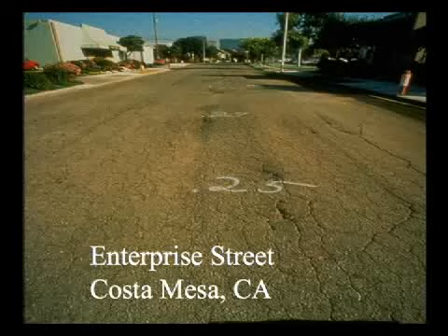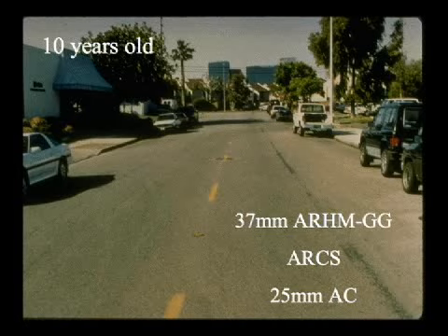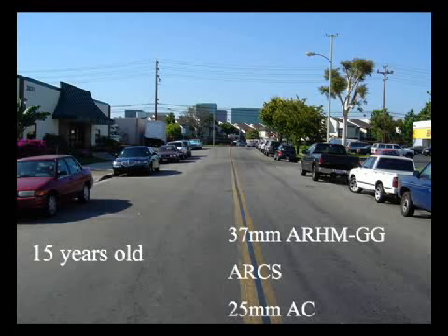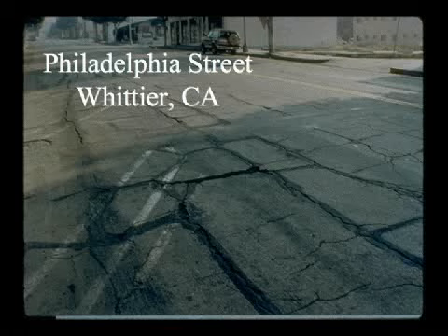Here was the other half of that project. You can see what the pavement looked like, all the alligator cracking. Here the picture is at 10 years, the same exact strategy was used. Here's a picture at 15 years. Two years prior to this, they put a slurry seal on the top of this. It's one of the only rubber projects that I know of that they went in and actually put a slurry on. It's still performing well today.